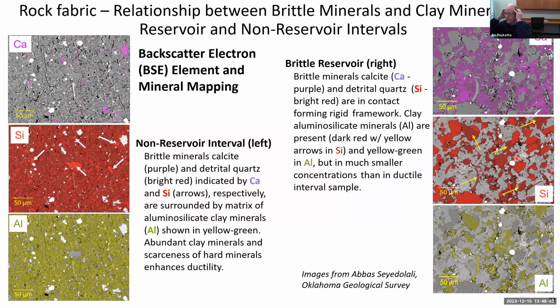Okay, let's zoom in and look at the microscopic level. Here's some backscatter element mapping, mineral mapping, and this is in the Caney. I'll start down here in the left side lower panel, showing this yellow-green color. And these are some images from Abbas's work when he was down at the survey. In this case, he chose this yellow-green color to represent aluminum. And aluminum, in this case, we're assuming is mostly from clay minerals. In the middle image here, the dark red, where the white arrows point, those are quartz. The deeper colored red is still the silicon detected in the clay minerals. And clay minerals are alumina silicate minerals, as we all know.